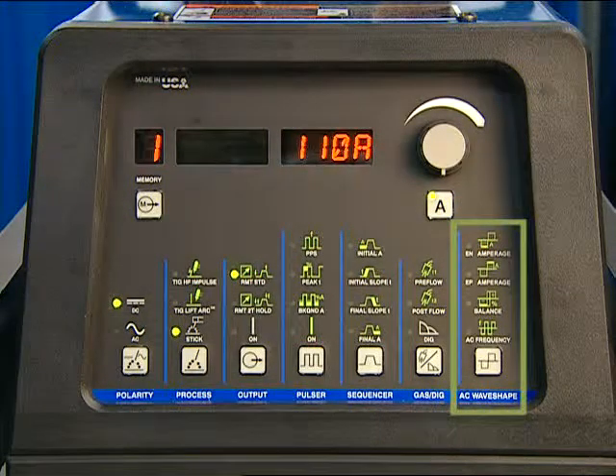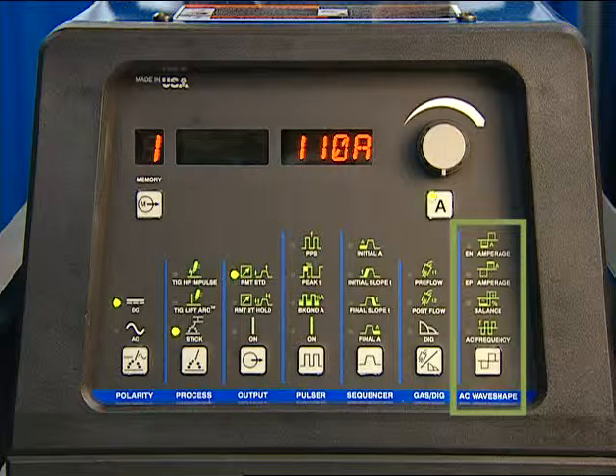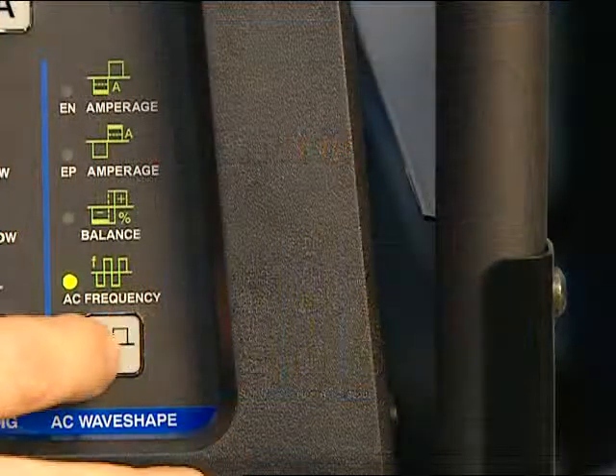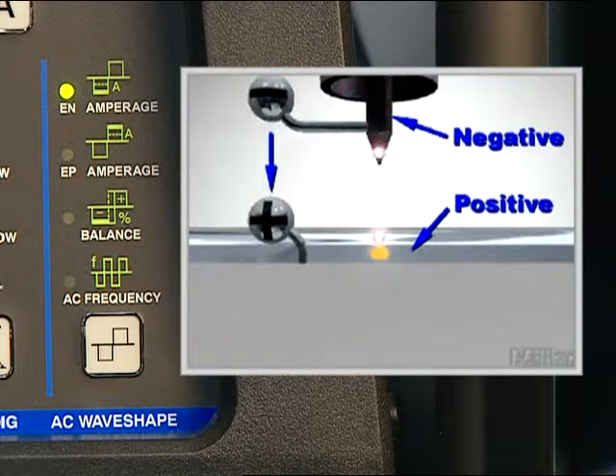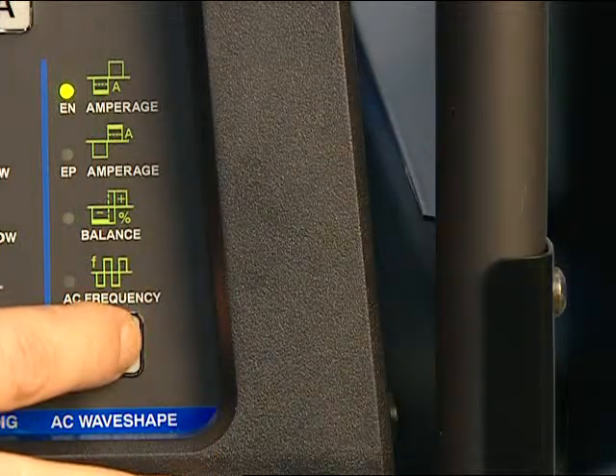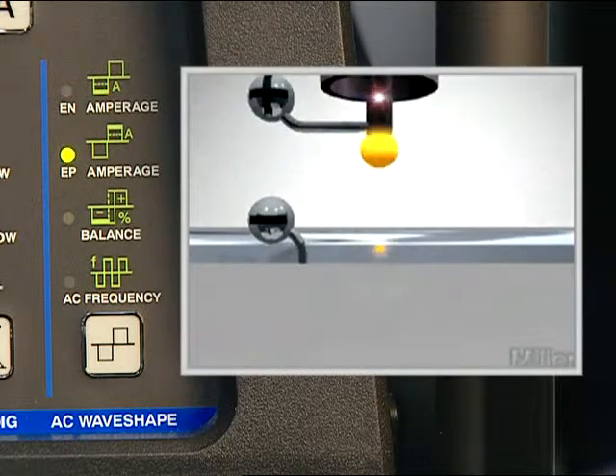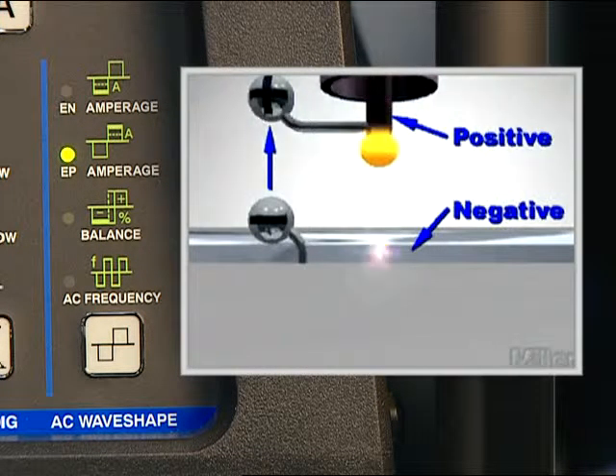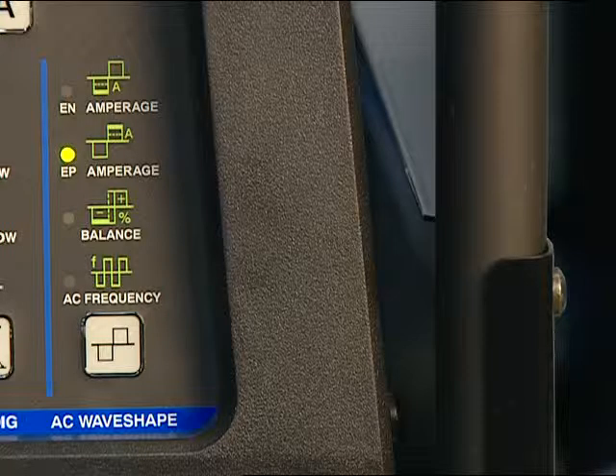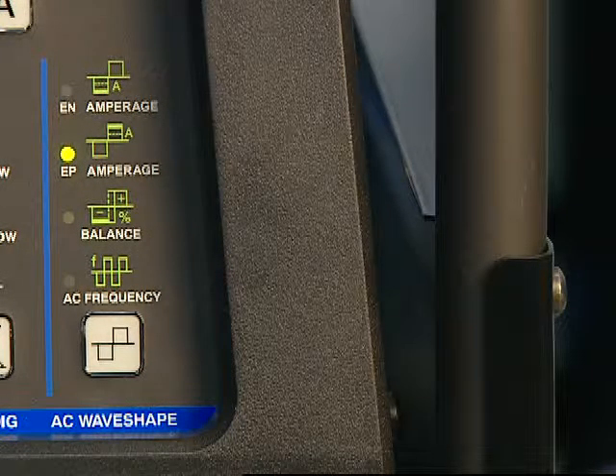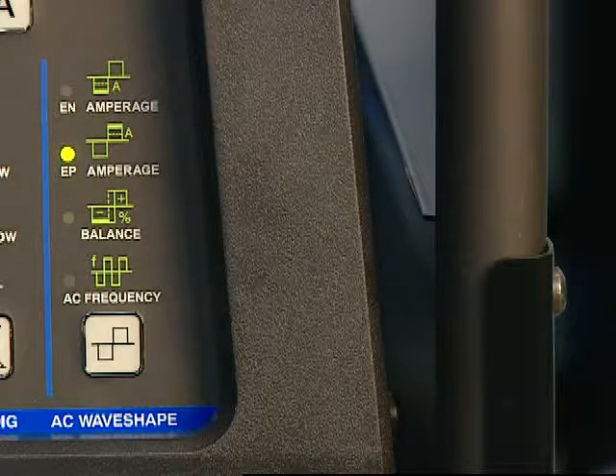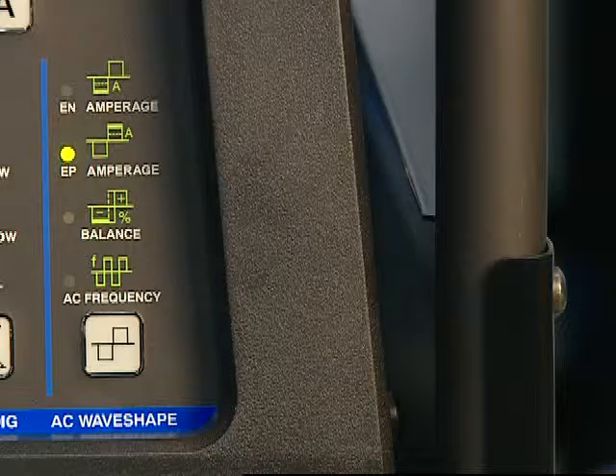These AC wave shape controls are Dynasty specific for TIG welding. Electrode negative allows us to adjust the electrode negative amps independently from the electrode positive amps. Electrode positive allows us to adjust the electrode positive amps independently from the electrode negative amps. To extend the tungsten life, we recommend a 1 to 3/4 ratio, 100 amps electrode negative and 75 amps electrode positive, and no more than a 2 to 1 ratio, 200 amps electrode negative and 100 amps electrode positive max.